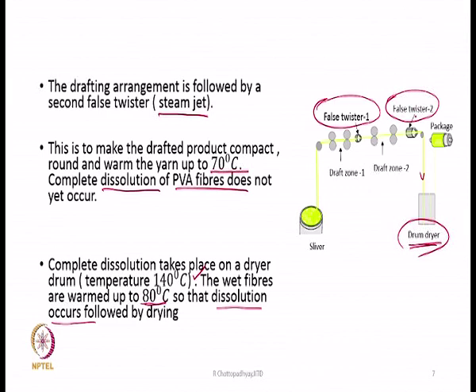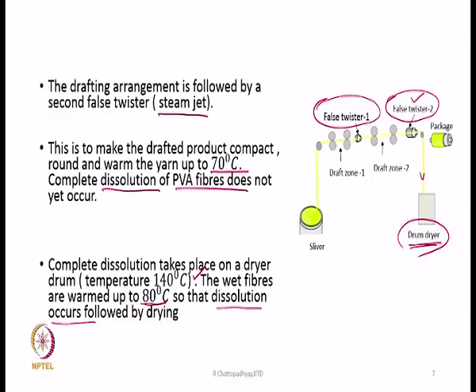So, here partial dissolution occurs when it is passing through the first twister. The temperature can go to the extent of 70 degrees centigrade. After that it goes to the dryer, where the temperature of the dryer is 140 degrees centigrade, but depending upon whatever residence time is there, the temperature of this yarn can go up to 80 degrees centigrade, so that all the PVA fibers are completely dissolved.